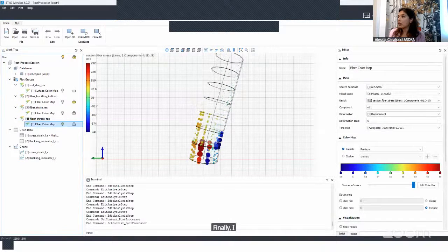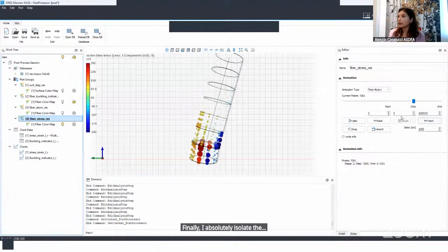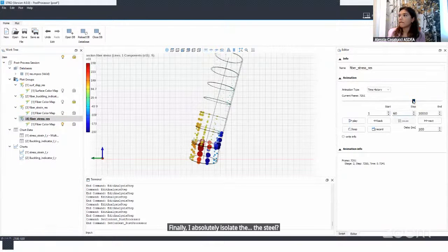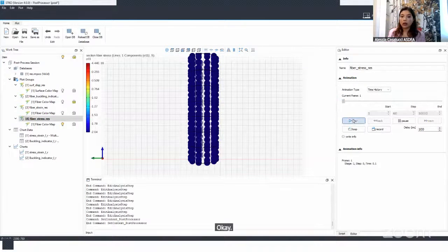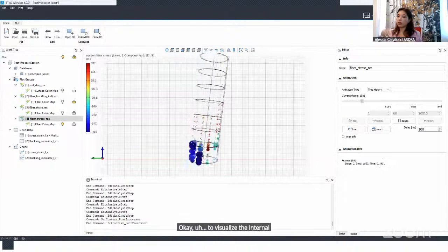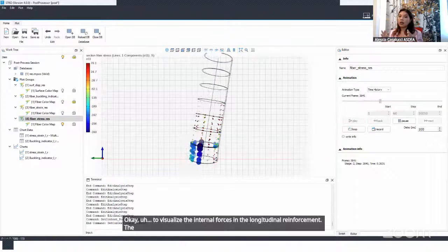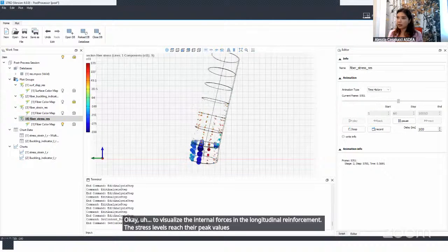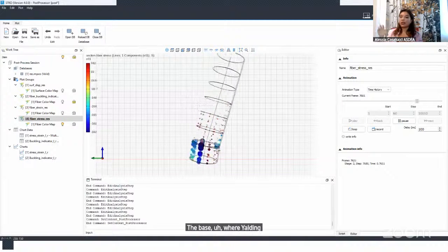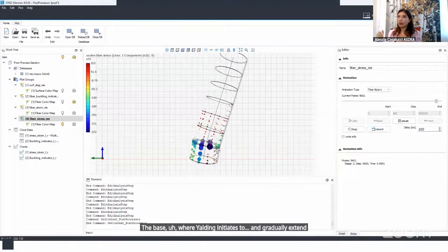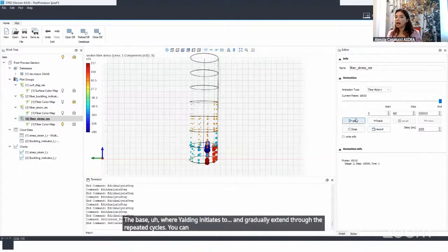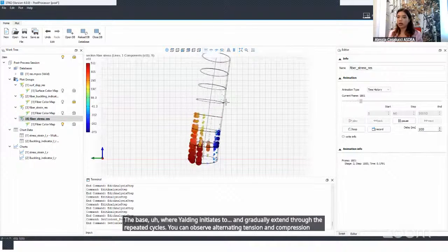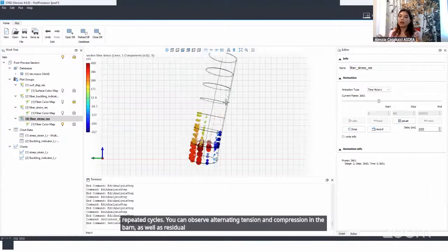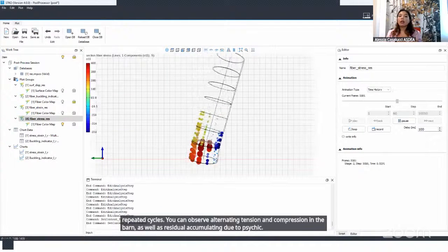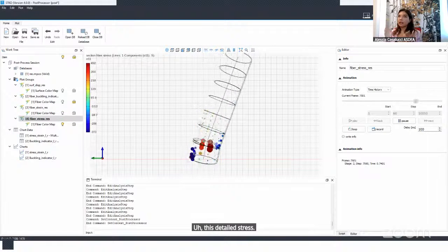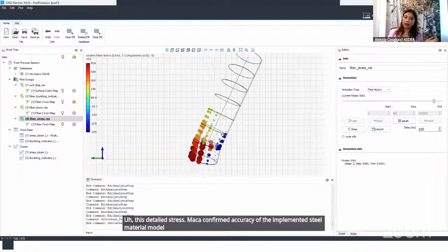Finally, I isolate the steel. Okay, to visualize the internal forces in the longitudinal reinforcement, the stress levels reach their peak values near the base, where yielding initiates and gradually extends through the repeated cycles. You can observe the alternating tension and compression in the bar, as well as residual stress accumulating due to cyclic plasticity. This detailed stress map confirmed the accuracy of the implemented steel material model in reproducing cyclic hardening and degradation.